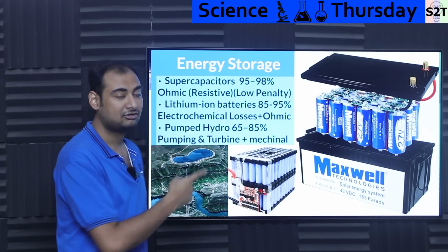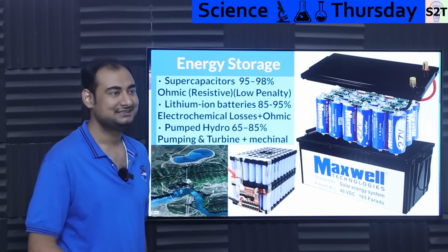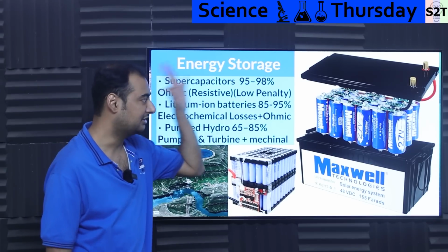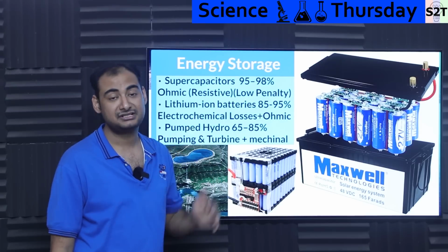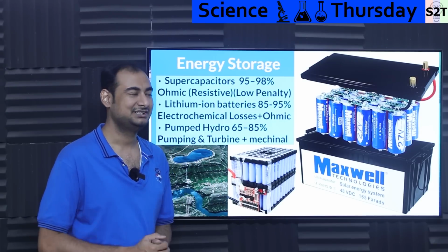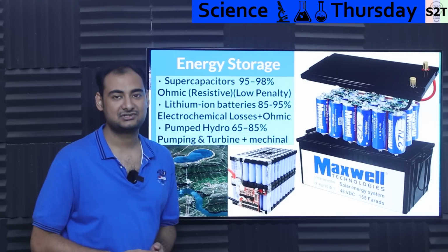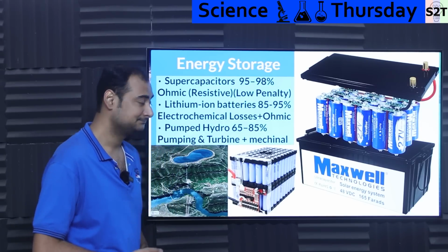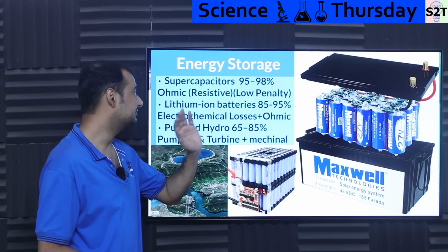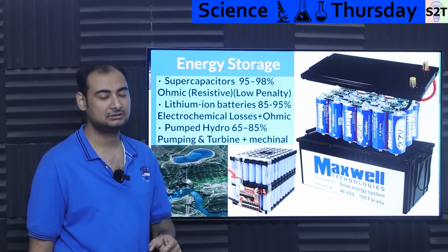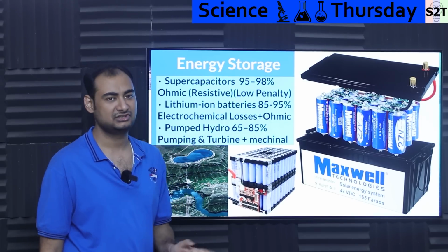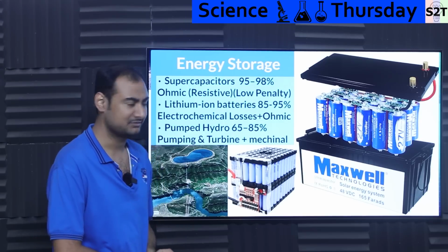The worst offender on those puppies is self-discharge. That's why nobody likes to use them. Basically, you dump 100 units into this, you can use 100 units like 5 seconds later. Awesome. But if you waited like one day, yeah, most will be gone. So the self-discharge rate is very brutal and very bad. Although for short duration, it is super awesome because it only has ohmic losses and the penalty is almost negligible. Like, you don't have to worry too much about it.